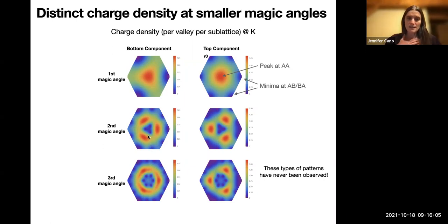The other thing that I'd like to say about this is that, as I said, the only difference in wave function between the first, second, and third magic angles is that function rho. And so you can understand where these nodes are coming from: these are all solutions. The wave function is always a solution to the Schrodinger equation. And there's going to be a family of solutions, and each one of those is going to be indexed by a different function rho. And so what we're really observing here is that at each solution, the wave function gets 3 more nodes. So here it has 0, then we get 3, then we have 6,